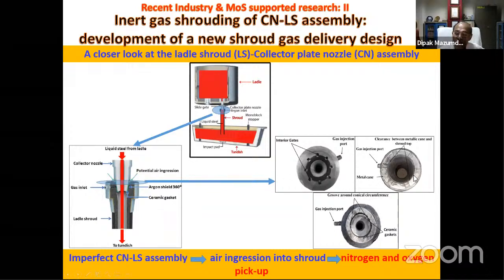Similarly, you have another design here, which is a metallic cone design, and you have a single discharge port with some kind of an external groove, which allows argon to be delivered around the shroud collector nozzle assembly, so that you do not get air ingression. If some gas goes, that will be argon, and that will not lead to reoxidation. That's a supposition. Let us see whether that supposition works or not, or whether it's legitimate or not. So if there is an imperfect collector nozzle ladle shroud assembly, air ingression is bound to happen.